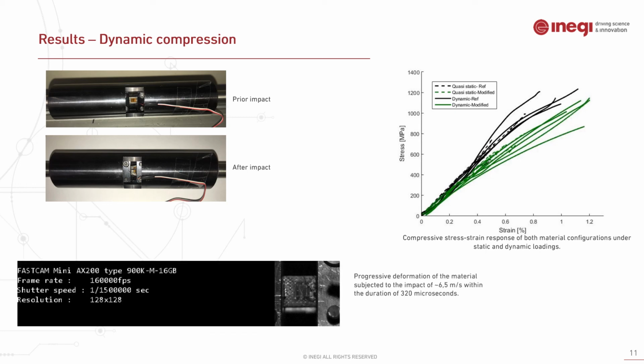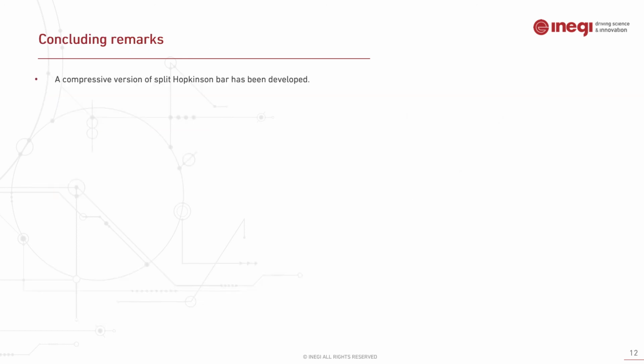And here we use the high-speed camera at 160,000 frames per second to monitor the failure initiation and propagation of the specimen subjected to the impact within a duration of 320 microseconds. And as you can see, the sample is showing a valid failure within the gauge section by splitting along the fiber orientation within the first stress pulse. This confirms the developed testing apparatus as well as the test fixture for dynamic compression experiments of composite laminates.